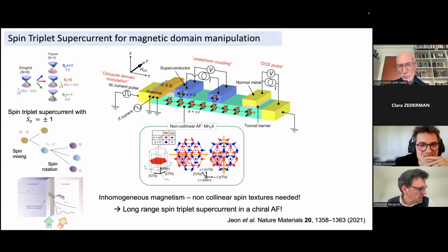And what we are currently doing is using those spin triplet supercurrents to manipulate magnetization. So one of these niobium electrodes we can replace with a magnetic electrode and use that spin triplet supercurrent to manipulate the magnetization in that second electrode. Actually, I'm not going to show you those data, but that's something that we believe we've now accomplished.